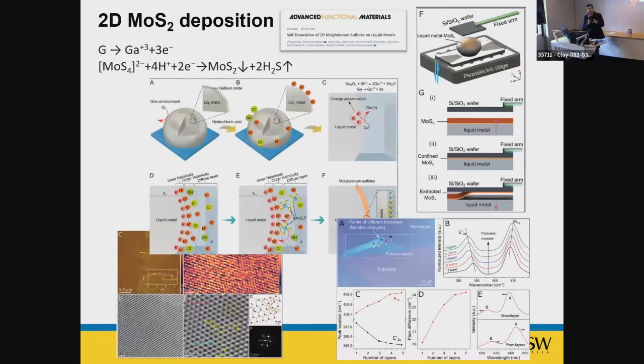Here's one example, molybdenum disulfide. So one of the problems, as I mentioned, is the CVD that came from the lab was not very good. We wanted to find other ways of having single crystalline molybdenum disulfide at relatively low temperature, and gallium gave us that opportunity. So we put gallium, liquid metal, in acidic environment. Gallium is released as gallium ion and enriches the surface with lots of electrons. So we brought the precursor of molybdenum near the surface, and it produced hydrogen sulfide, very low amount. We're not talking about even parts per billion, so it's not dangerous. And molybdenum disulfide produced on the surface.